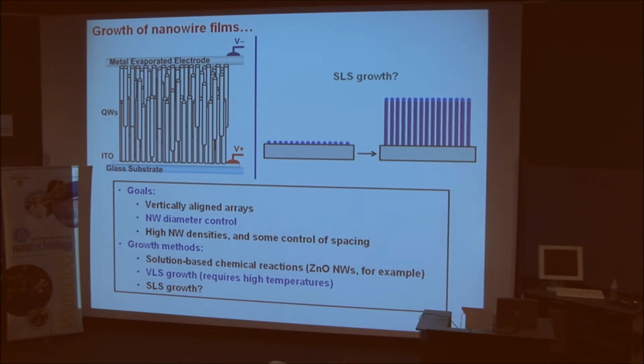Okay, let me finish with just a few results on growth of nanowire films. So if you want to, for example, make solar cells, it might be convenient to be able to grow the wires as arrays, vertically oriented arrays, right from some appropriate substrate. And when we do this, we'd like to be able to control the nanowire diameter and the spacing and density of the nanowires on the substrate. Certainly you can look in the literature and find some success in growing these sorts of arrays for zinc oxide nanowires, for example.